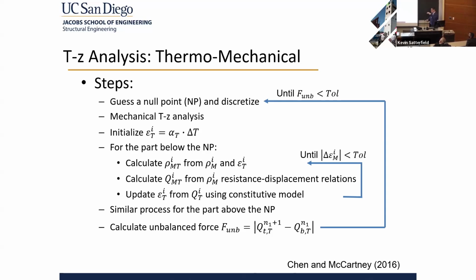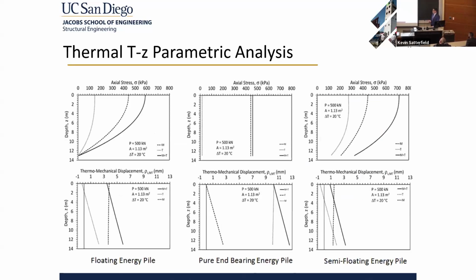So if there's no restraints at all, the entire pile would just expand by alpha delta T. If there is restraint, it's going to be less than that. So we can go through some different examples. I will show some comparisons with field data later, but these are examples for a floating energy pile where there's no restraint to the toe, a pure end-bearing pile where there's no side shear, and then a semi-floating energy pile, which is probably most realistic what we would expect. So high stresses at the head and low stresses at the toe.